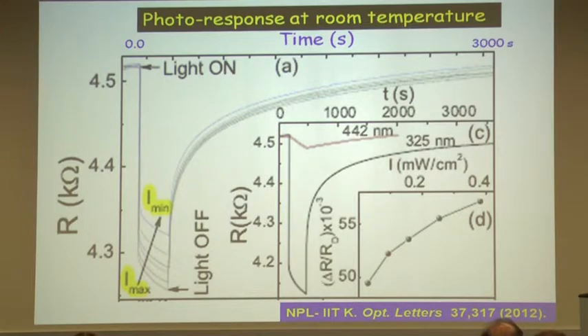About 7 to 8 hours to get back to the original state. And if I keep on increasing the intensity, the response becomes more. But now let us see what happens when I use the laser light. When I use 442 nm, which is blue, and 10 times brighter, there's hardly any change.